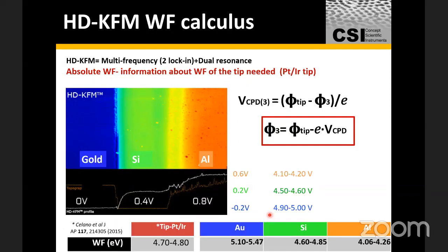And this is a nice illustration of how we calibrate some of these measurements. If you set the work function of gold, for example, at 0, you're then able to make the relative measurements on something like silicon and aluminium, in this measurement here. So this is about calibrating the setup, which is really measuring a relative interaction between two surfaces to get an absolute value of the work function of the surface. So you need to calibrate it against a known material that has a known work function and bring that to 0.